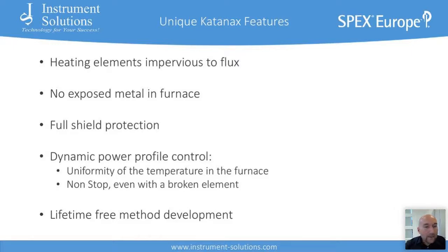The dynamic power profile control takes care of uniformity of the temperature in the entire furnace, and it keeps running even if one of the elements breaks down. These specific heating elements have a very long lifetime, but they have an ending lifetime. So if one breaks down, the others compensate during the run. And also you can keep using your system until there's time to replace the heating element.